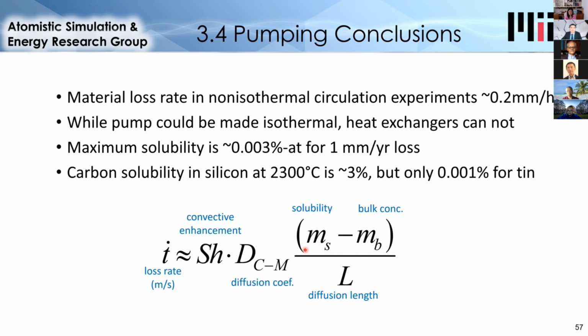This equation is basically just mass transfer, including a convective enhancement called the Sherwood number, which is analogous to the Nusselt number for heat transfer. So I just used a value of 4 here, which is for laminar flow. The diffusion length in this case could be like the radius of a pipe. And so in this case, I use 50 millimeters. So we see that we need something on the order of 0.003 atom percent solubility. And one material that I mentioned earlier that has solubility even lower than this is tin.